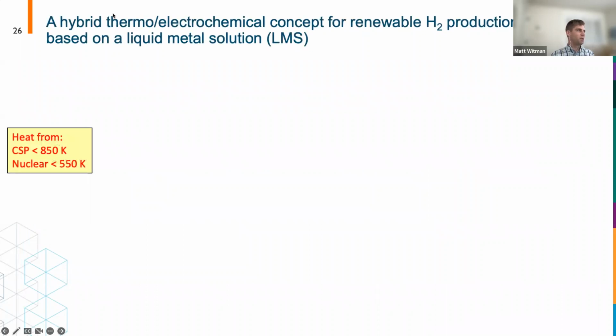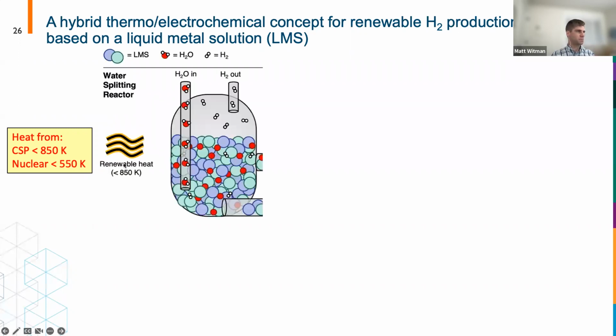So my colleagues had proposed this hybrid thermoelectrochemical concept for renewable hydrogen production based on liquid metals. And the motivation is that current concentrating solar power cannot reach the temperatures that we need for the previous application we just showed, at least not at a commercial scale. So we're looking for things that can split water below 850 Kelvin if it's coming from concentrating solar, or even below 550 Kelvin, which is the waste heat from a nuclear reactor.